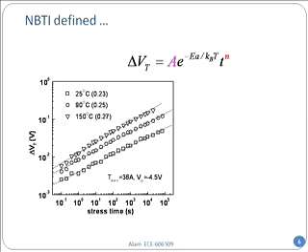Now, for NBTI, this threshold voltage shift is given by this very strange formula. You have a constant and exponential dependence on temperature. You see, if the temperature is high, then the degradation is more, right? So you can see that that's exactly what is seen: the 150 degree, the triangle down, is significantly higher than the 25 degrees C, that's the square.